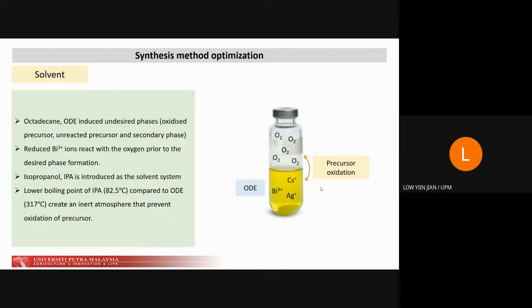As a result, the CsBr to the BiBr3 and to the AgBr precursor ratio in the reactant solution is altered by the bismuth bromide oxide formation, and tends to form a more stable secondary perovskite structure with some leftover impurities. Then, without a huge modification, IPA is introduced into this system and successfully synthesized the desired phases with high purity.